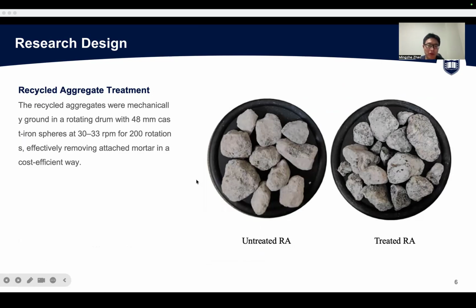Before the study starts, we have to treat the recycled aggregate first to remove the attached mortar. The recycled aggregate is put in a rotating drum for 200 rotations. This can effectively remove the attached mortar. You can see the photos of the untreated RA and the treated RA. There are some differences.